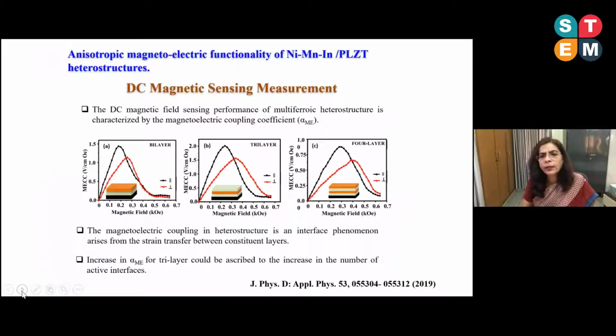Then another work we did with this FSMA-based structure was DC magnetic field sensing, for which we made a bilayer, tri-layer and 4-layer of this FSMA-PZT. We measured alpha, the coupling coefficient, versus the changing magnetic field, and found that it remains linear up to a certain value of field, let's say 0.3, and then becomes non-linear.